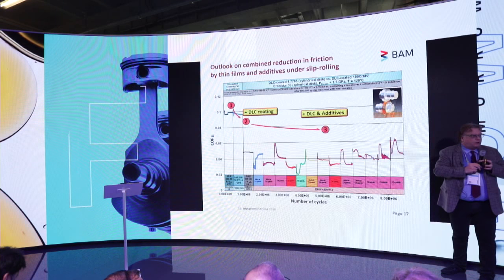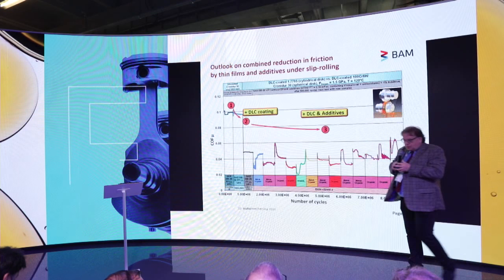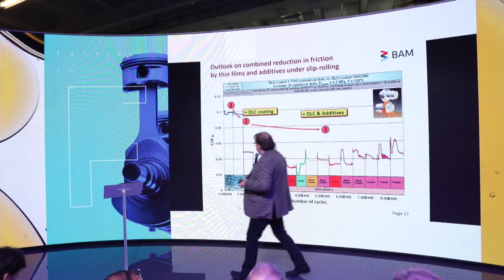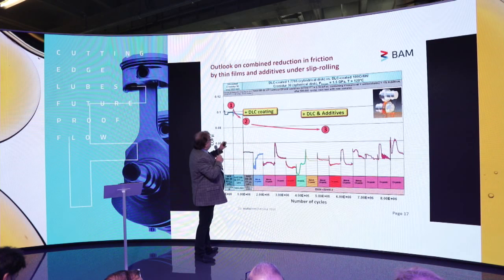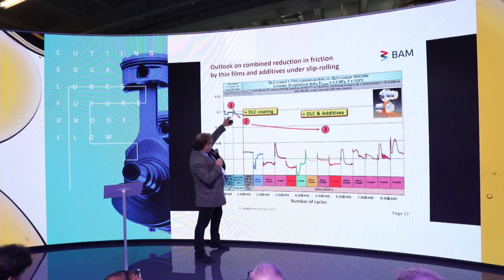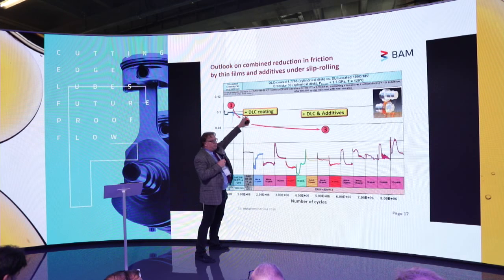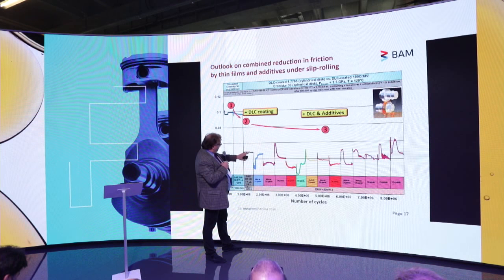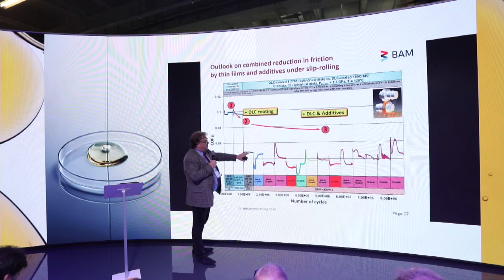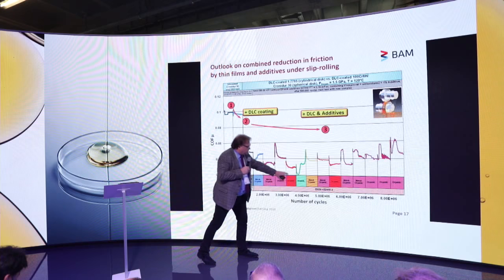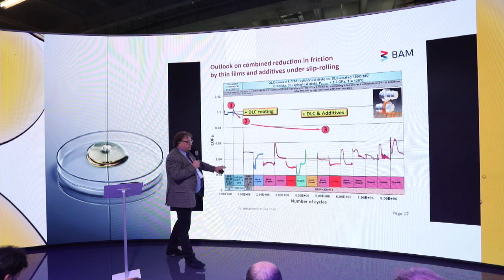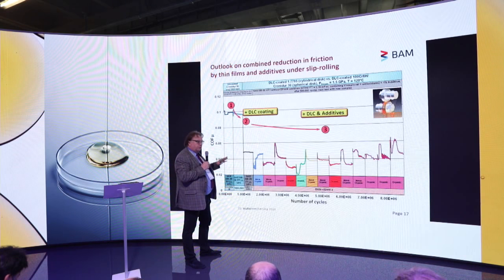The question is now, what happens when you combine metallurgy and additives? Here we start uncoated. Now we put the coating, friction down, and now coating and chemistry, we can still go down quite low, 0.03. So this is a toolbox to reduce friction, but you have different responsibilities.